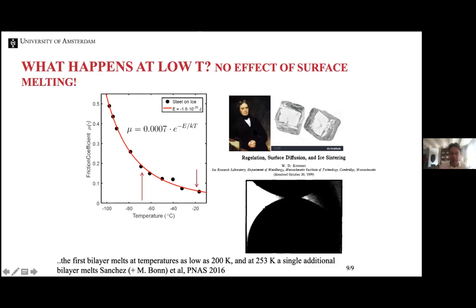And that's basically due to Faraday, who took 2 ice cubes outside on a cold day, put them together, and then they sintered together. You couldn't detach them anymore, one from the other. And so Faraday's reasoning was that since the water molecules have to come into the register of the crystalline lattice, they must be mobile, and therefore there must be a water layer.